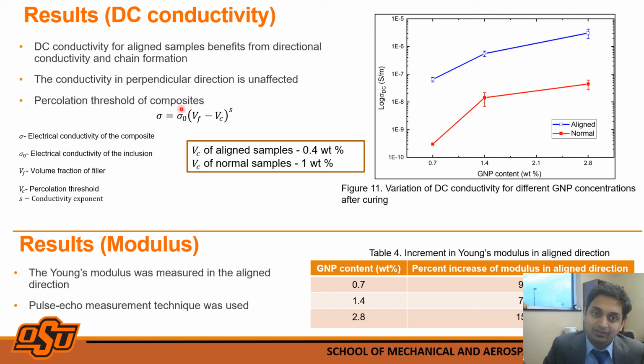We can also calculate the percolation threshold of the composite. It basically tells us the minimum amount of particles required to make the insulating polymer a conductive polymer. For aligned samples, it was 0.4 weight%. For normal samples, it was 1 weight%. So a lower weight of graphene is required to achieve the electrical percolation threshold.